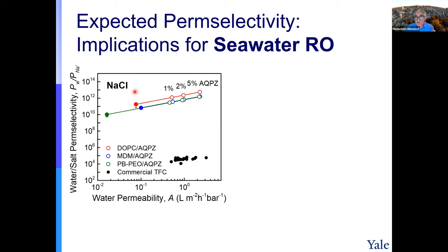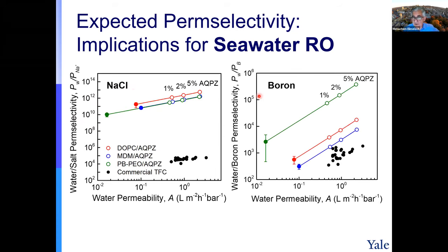This salt will not go through this block copolymer because it's hydrophobic, and the channels, if they are not effective, will remove all the salt. And the same thing we did for the boron. Boron is uncharged, so it can go through. We did some measurements, and it can go to some degree through this block copolymer bilayer.